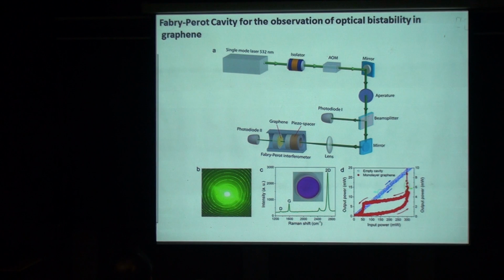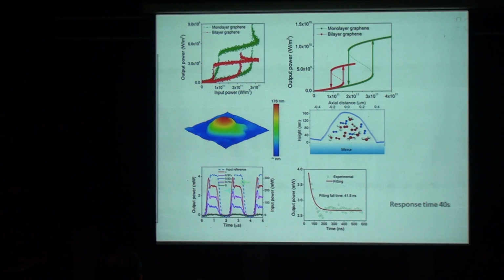You can change the optical path length by 266 nanometer. It's impossible for a single layer graphene which is flat, you see, because the absorptive path length is too short. Under the intense laser irradiation, it starts to form bubbles on the graphene, and with the additional vertical sidewall, it has a dispersive interaction. Then it gives rise to this optical bistability. Without the graphene, input power and output power are linear. Once you put the graphene in, you get a hysteresis. Now, this is the characteristic of optical bistability. Once you put in 1 input power, you can get 2 output powers at resonance. Now, this is very useful as a basis of an optical switch, you see. So, it's a very interesting effect.